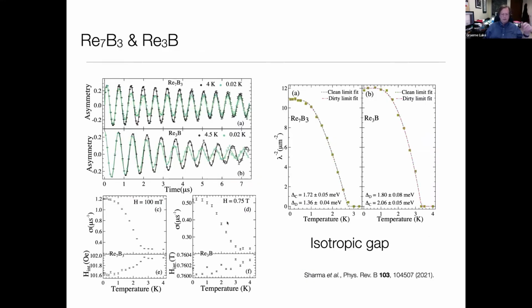Here's another interesting new material that we've recently looked at, where you see again, measuring the temperature dependence of this broadening or this relaxation as a function of temperature, and then fitting its temperature dependence, you can actually see that these materials have two gaps, both of which have S-wave symmetry, and you can get fairly precise measurements of these by fitting them to theory.